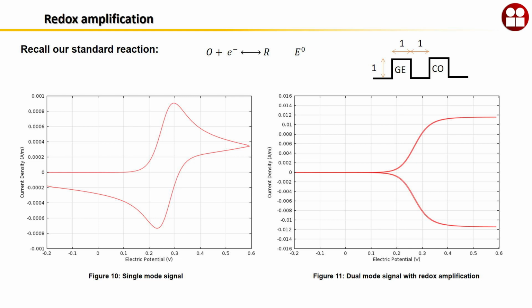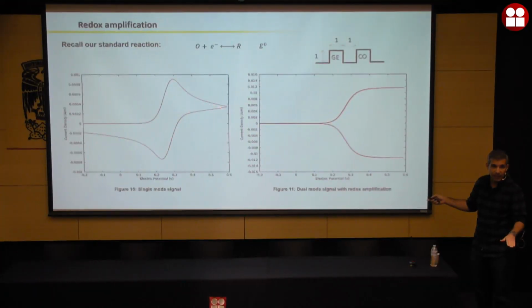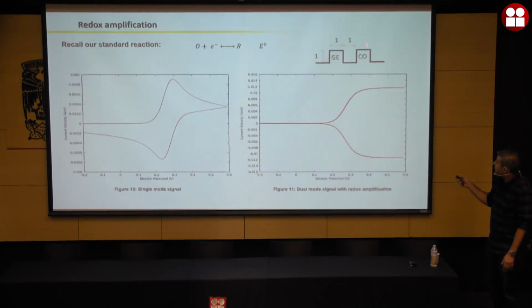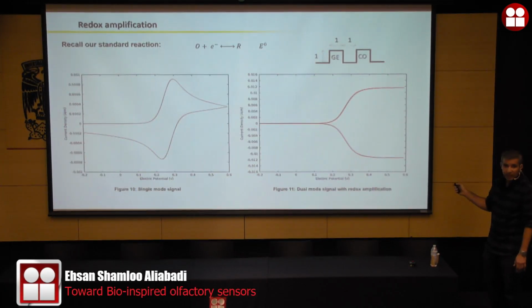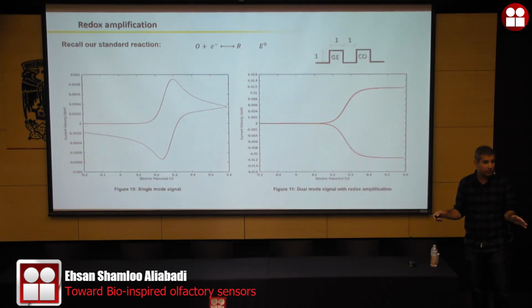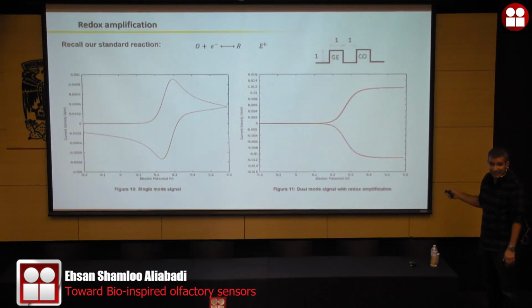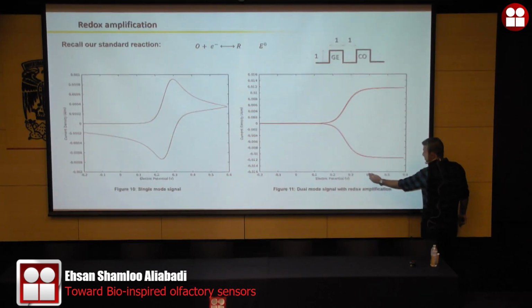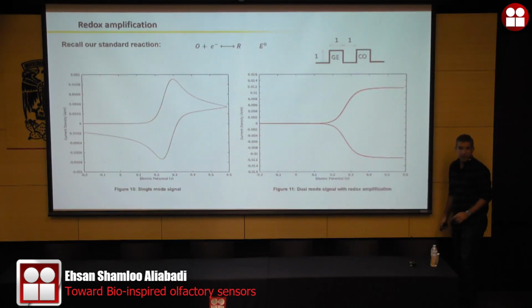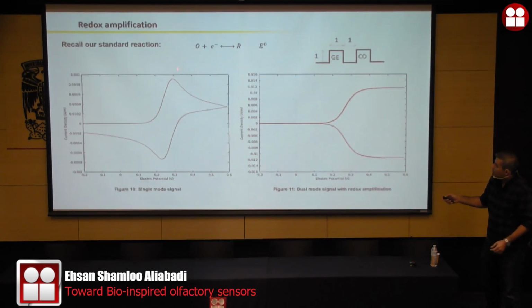Now I want you guys to look at these two signals. I mentioned about this signal. You start applying the potential, you start consuming the electrochemical species, and at this point you're out of the electrochemical species on the surface of your electrode, and you see that your signal decays, and then it goes back. In the opposite side, when I have two electrodes at this configuration, you see that the signal goes up and plateaus out. It stays flat as long as I'm applying the potential. This is what we call a steady state. It doesn't matter if I'm measuring at this potential, I'm on a flat line. This is the beauty of the system, right? But here, post-processing is kind of difficult.